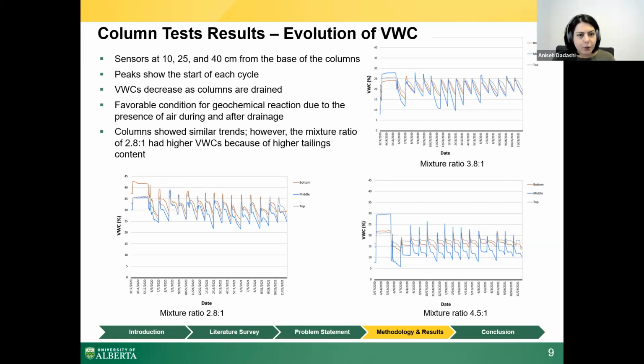These graphs show favorable conditions for geochemical reactions because of the presence of air during and after drainage. In general, columns showed similar trends, but the column with mixture ratio of 2.8 waste rock to 1 tailings had higher volumetric water content because this column had more tailings and retained more water.